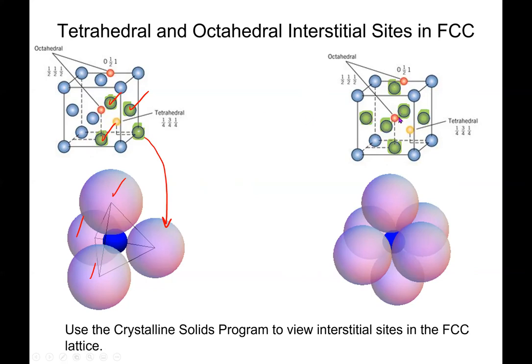The one in the center, if I look over here, there's a big hole in the face-centered cubic structure right in the center of the body. You had a position one half, one half, one half. And if I take the neighboring six face atoms, those are actually all touching. You can see that down here. And then there's the site right in the middle. And this is referred to as an octahedron. I connect all these sides. You can see here this forms an octahedron. So this is an octahedral site. And a similar kind of site here for the edges. If we were to put on the rest of the blue lattice, we'd actually see that this is similar. And again, it forms an octahedral site.